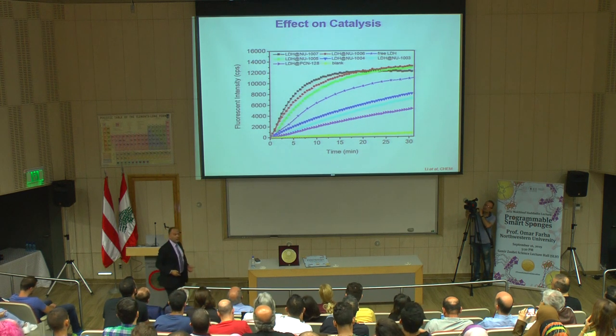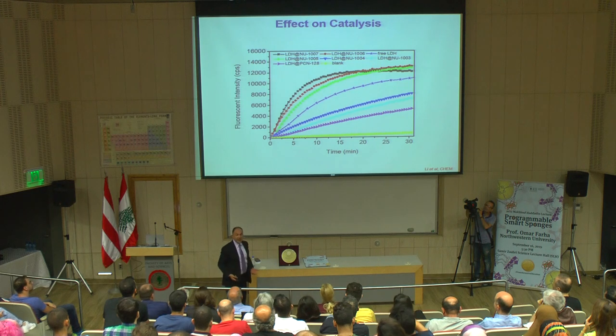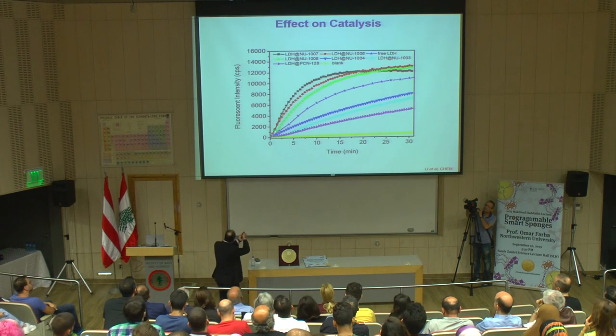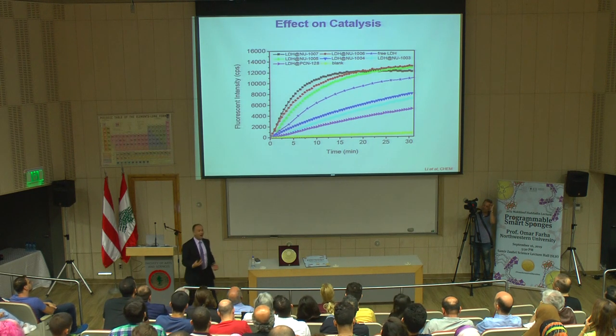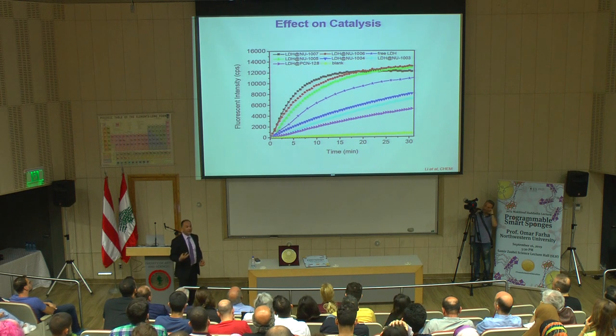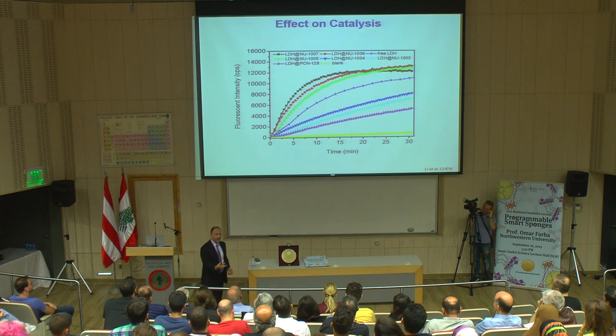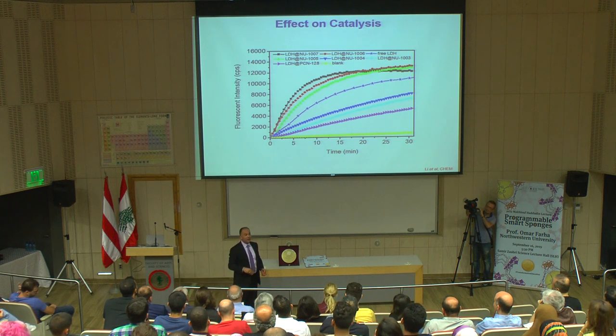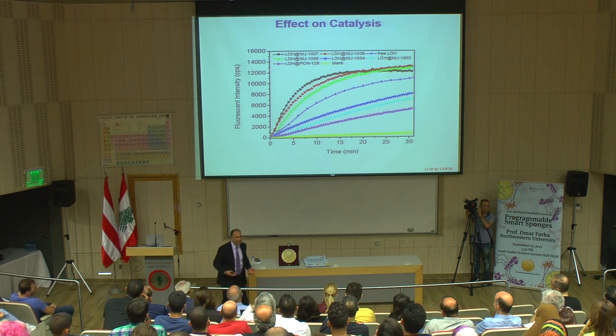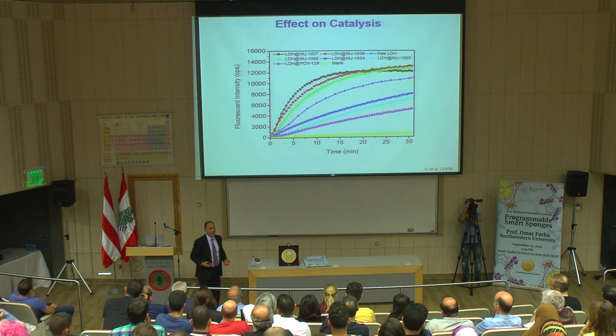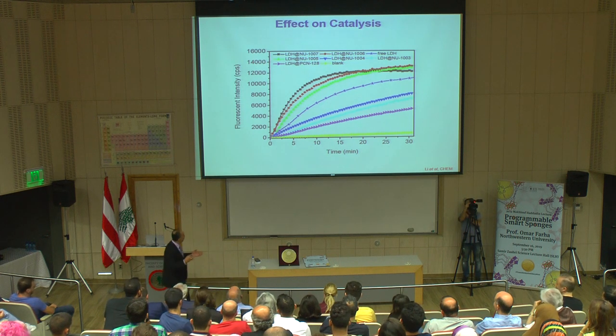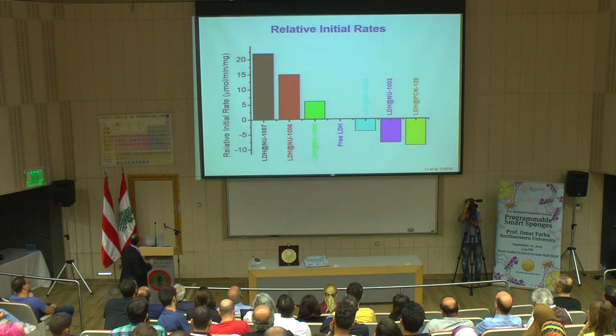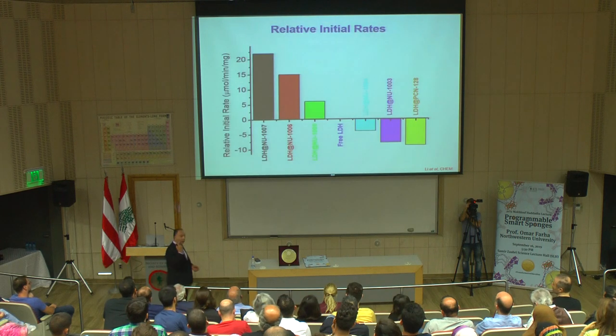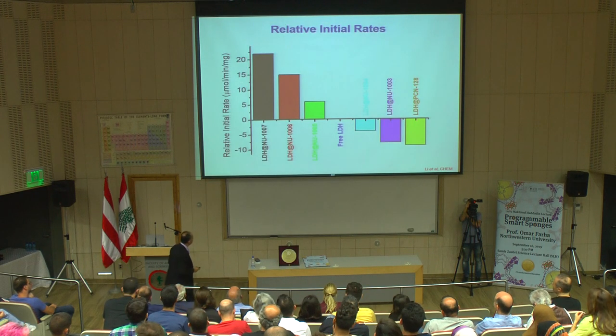Once you remove the diffusion limitation, besides the extra stability, now we have three materials with even higher initial rate of catalysis than the homogeneous. That's a second example. I didn't give you any explanation of why we think that's happening, but hopefully during Q&A we could go through that as well. But we see that it's not only for one example, it's more general than we think.